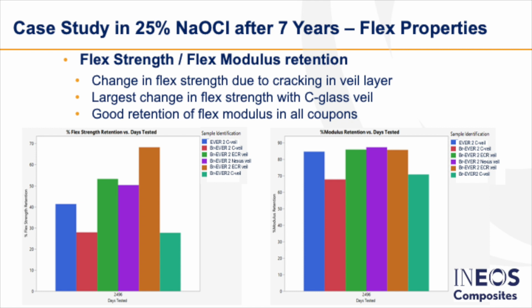Looking at a summary of the flex properties, over here is the flex strength, and these values were a little bit lower just because of the cracking that was present in the veil layer. And then overall, all of the coupons had very good flex modulus retention after those 7 years.